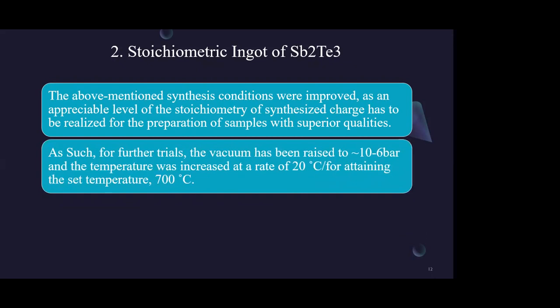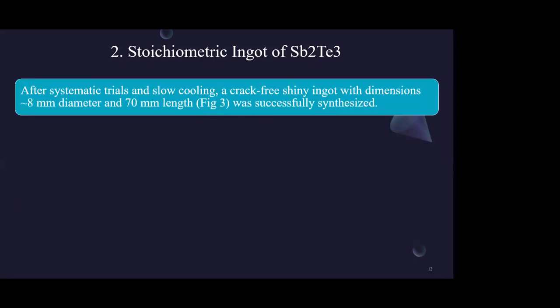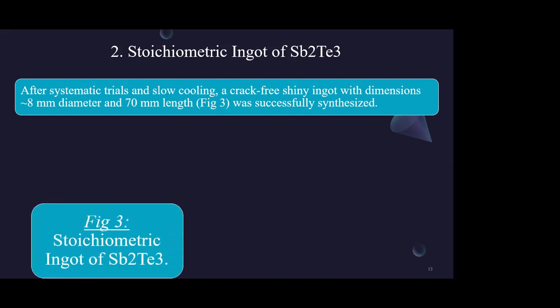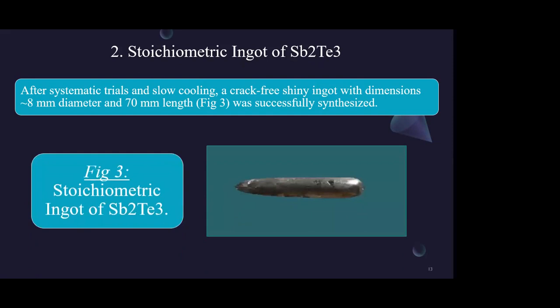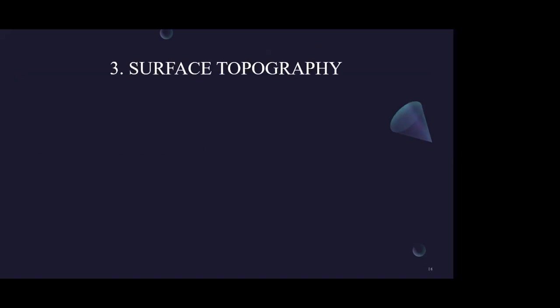As such, for further trials, the vacuum has been raised to approximately 10^-6 bar and the temperature was increased at a rate of 20 degrees Celsius per step for attaining a set temperature of 700 degrees Celsius. After systematic trials and slow cooling, a crack-free shiny ingot with dimensions approximately 8 millimeter diameter and 70 millimeter length was successfully synthesized. And this is the crystal that was synthesized with the second process.